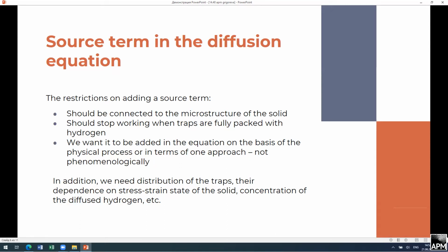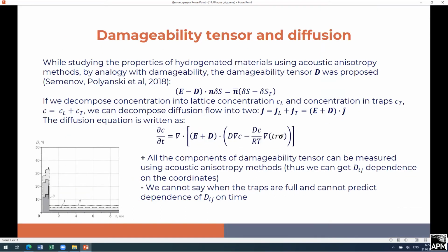And of course, we want this source, which depends on traps, to depend also on the stress-strain state of the solid, concentration of diffused hydrogen, and so on. Everything that can affect the microstructure of the material. So the first idea was to take into account the damageability tensor, which appeared first in works of Polyanski and which showed non-uniform distribution of microcracks and microvoids in metal.